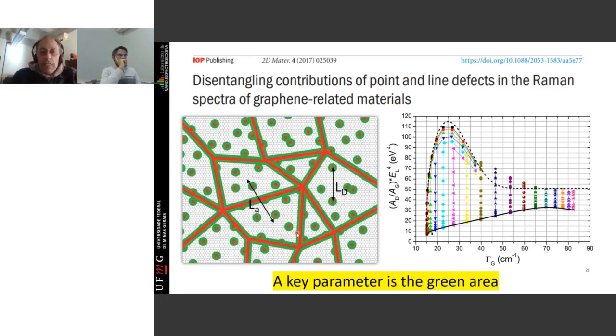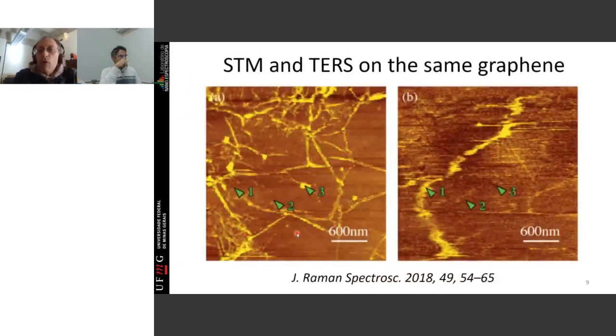So all this story is on what we call, let me call it a micro-Raman. We are in the microscopic range, and we want to evolve and go into the nanoscopic range. We want to do nano optics or nano-Raman imaging, okay? What you see here are those grain boundaries, like I showed. This is a piece of graphene, okay, with the grain boundaries. And this image is made with STM, scanning tunneling microscopy, because the electronic structure at the grain boundary is different from the electronic structure at the nicely organized graphene. And then you can image the graphene with these defects. And what you see here, this is a work that we did back in 2017-18.